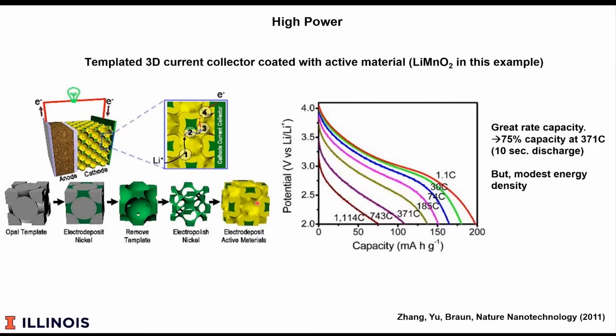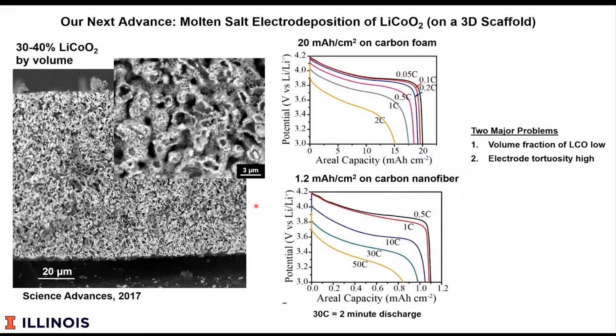So on the cathode, this approach has a number of challenges. And we've since moved away from this approach on the cathode, as I'll mention. On the anode, it indeed does have some very important advantages. The other problem, and the one that we overcame reasonably quickly, was that initially we weren't that good at growing material. So in an intermediate step, we determined how to do electrodeposition of lithium cobalt oxide. And so this is, we use a molten salt. I'll show some of the details on the next few slides.